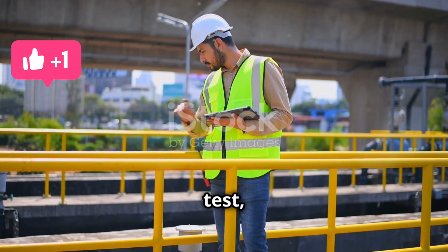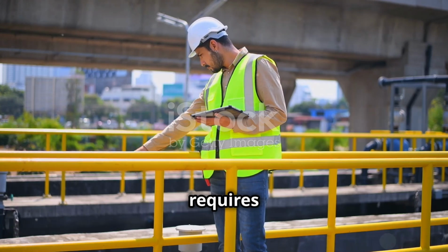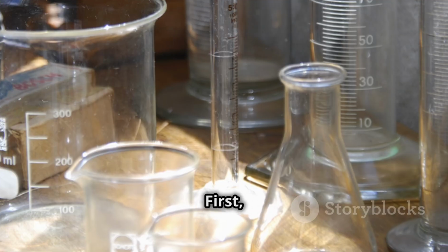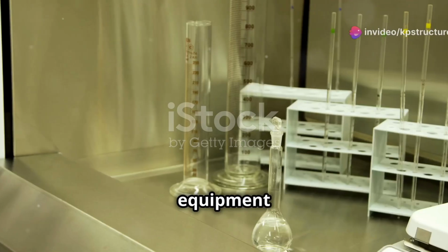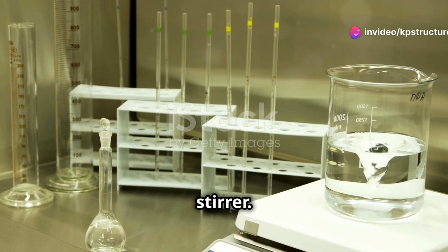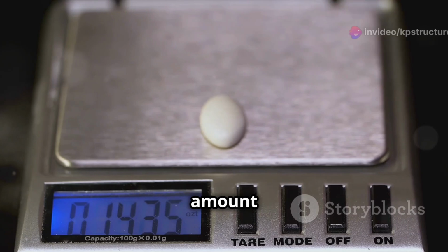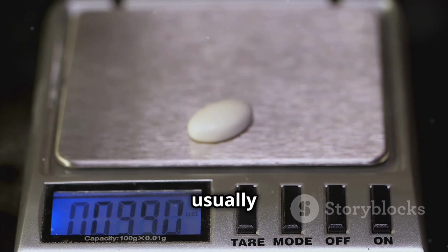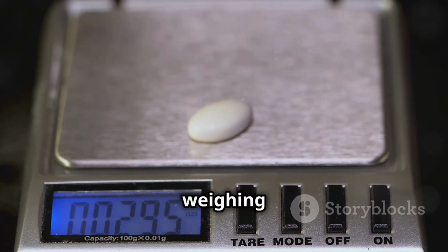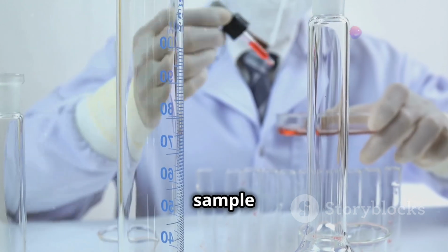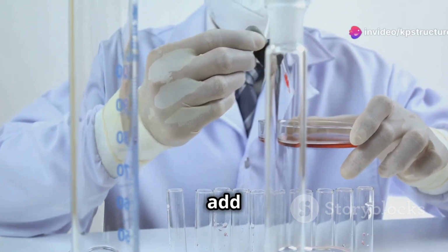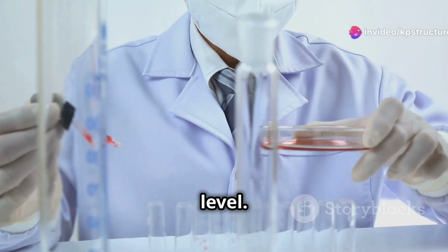The silt content test, while straightforward, requires precision for accurate results. First, gather the necessary equipment: a graduated cylinder, a beaker, a weighing scale, and a stirrer. Weigh a specific amount of dry, fine aggregate sample, usually 50 grams, using the weighing scale. Pour the weighed sample into the graduated cylinder and add water until it reaches the marked level.